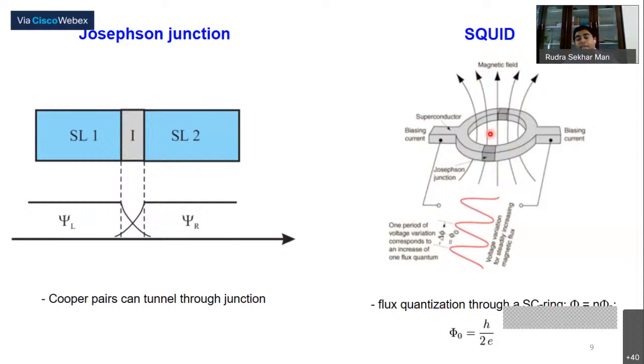If you put some magnetic sample here, and you apply a magnetic field, then the flux changes. And that flux you can measure in the flux quantization. You can also calculate this equation, the flux quantum is the Planck constant h by 2e, and 2e is nothing but this Cooper pair, because 2 electrons, and that's why 2e. And this flux you can measure really precisely, a very sensitive technique.